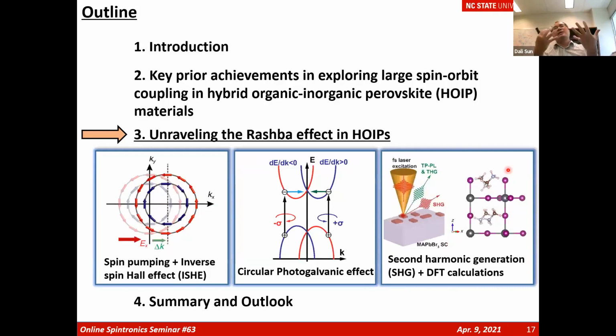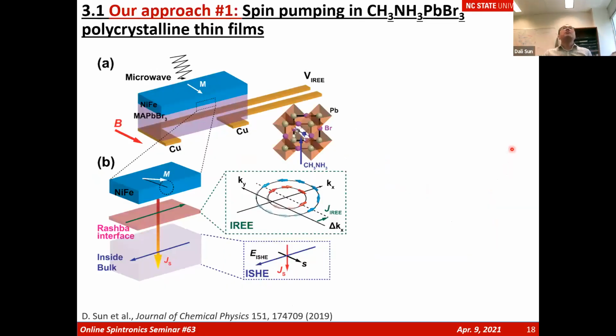Well, so that gave us the motivation to further study the Rashba effect in the hybrid perovskite materials using three different methods: spin pumping, circular photogalvanic effect, and second harmonic generation. Well, first of all, we tried the spin pumping method in the polycrystalline thin film.